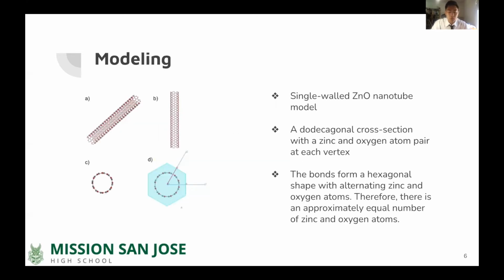So here's the model we put into Material Studio. The simulation of zinc oxide nanotubes is run to study their properties, since it is a promising option. For the zinc oxide nanotube model, we created a single wall, as shown in the figure. The nanotubes have a dodecagonal cross-section with a zinc and oxygen atom pair at each vertex. The bonds form a hexagonal shape with alternating zinc and oxygen atoms. Therefore, there's an approximately equal number of zinc and oxygen atoms.